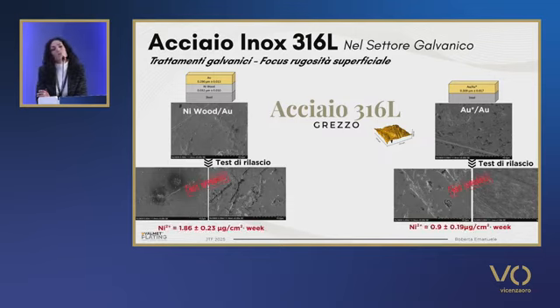As for the results, these are all averages of 3 repetitions, and as you see, the release tests are higher than allowed by the law. For the samples produced with the golden layer, the figure is halved. You might think that the nickel is released by the substrate of Wood's nickel, and yet this is counterintuitive because nickel is not included in the substrate.